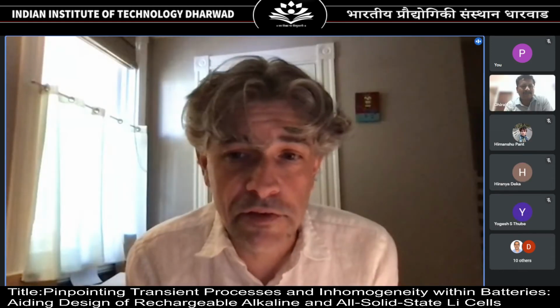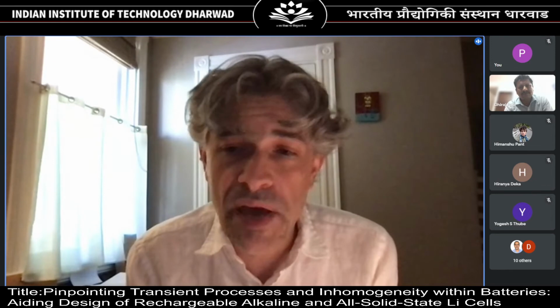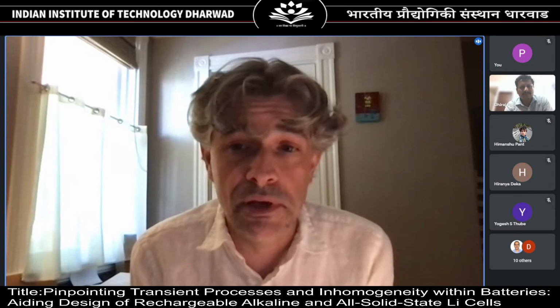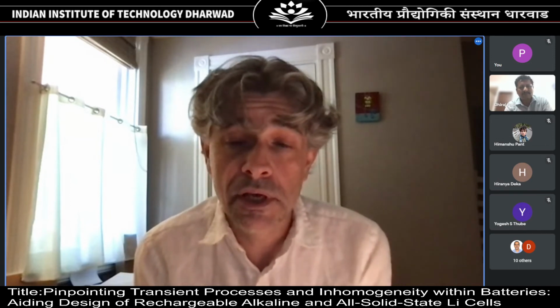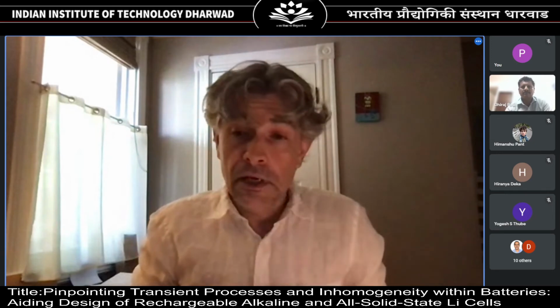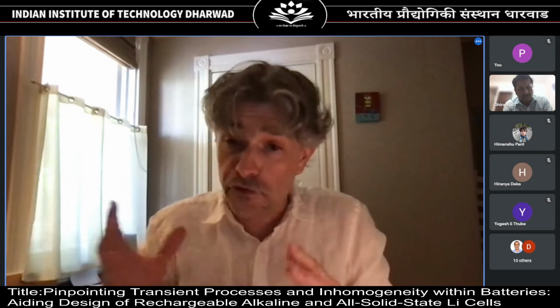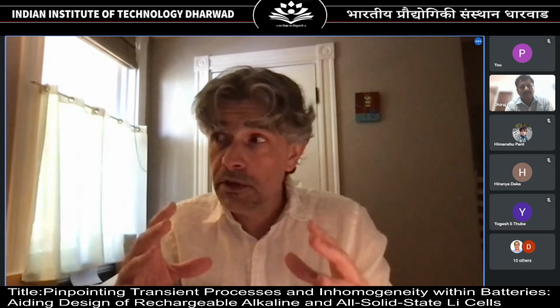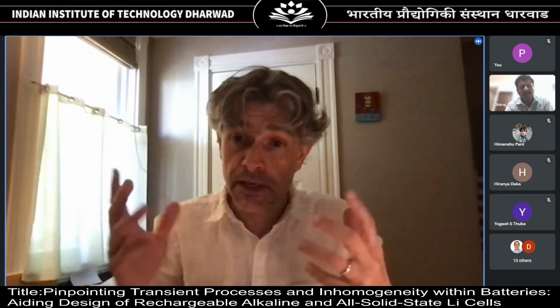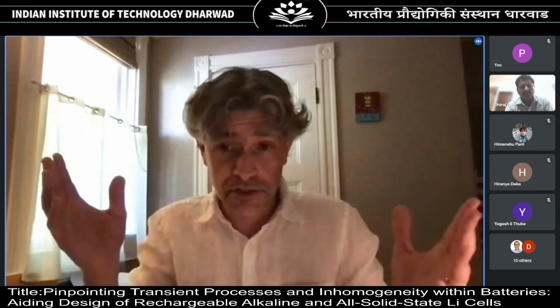To predict the shelf life, I don't know. The battery itself has many failure modes, and you will have different failure modes depending on what the battery has experienced. So shelf life, like you said, probably doesn't involve any fracture, at least of a zinc MnO2 battery. Shelf life probably involves surface poisoning. You get reactions at surfaces, and like I said, it has lots of surface inside of it, and so more and more surface reactions happen, and the battery degrades that way.